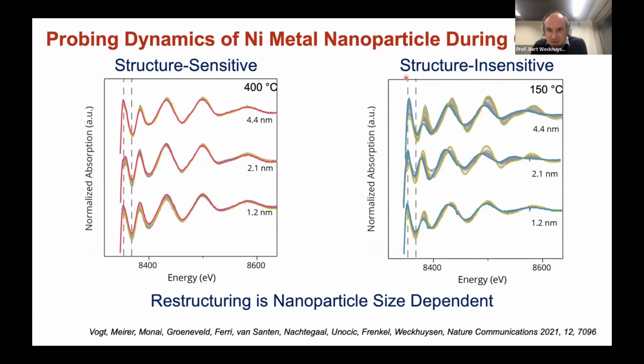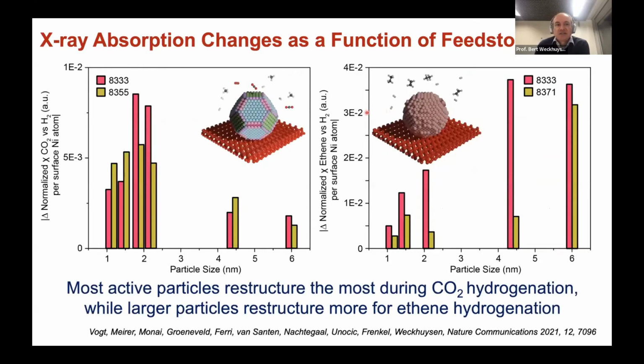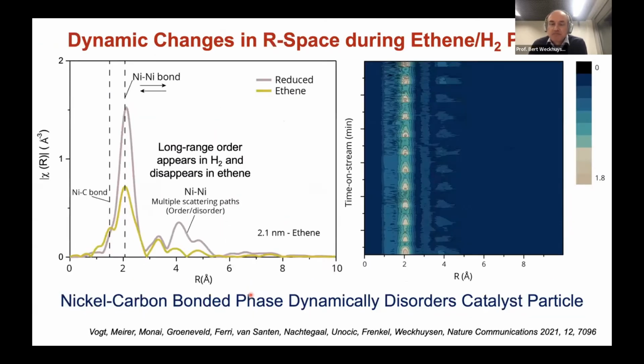Can you now, by focusing on certain energies, see what is happening? Here I show you two energies which are representative, as a function of the metal nanoparticle. We actually blow up the changes by having this normalized. But in any case, you can see that there are changes: the most active particles restructure the most during CO2 hydrogenation. And in the case of ethylene, the larger particles restructure more.